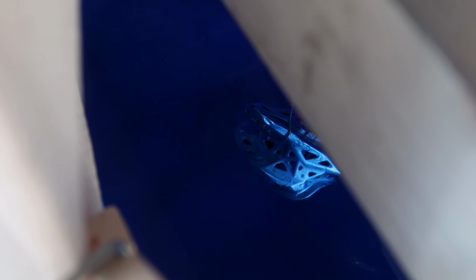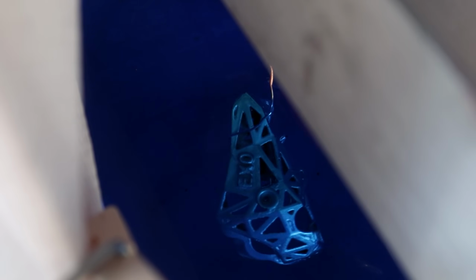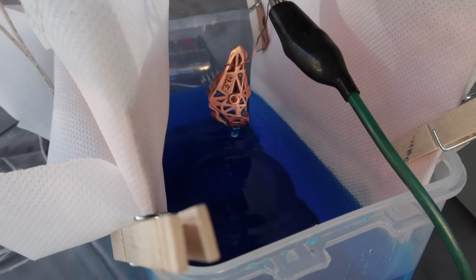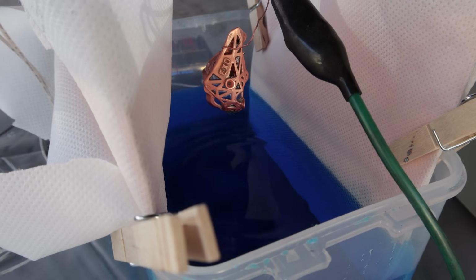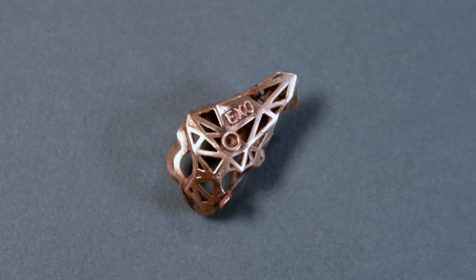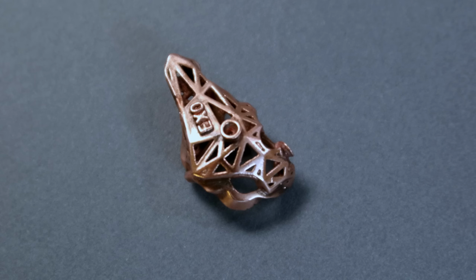You can see the results are looking pretty good so far. The plating's building up pretty evenly across the entire lattice. You can see the process worked really well with these parts. It's a little matte, but I think once I buff it down, it should get a really nice bright coating to everything. So yeah, this is the first lattice part after being polished down. I just hit it with a Dremel for a couple minutes, and the shine really came through.